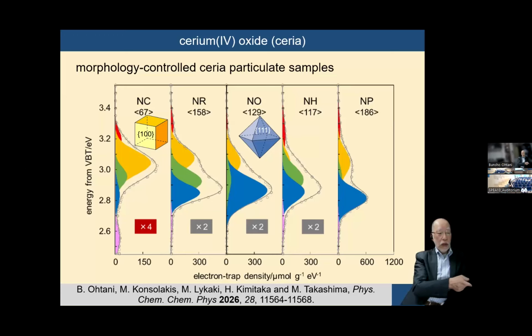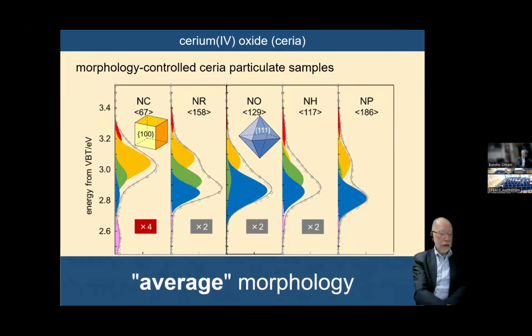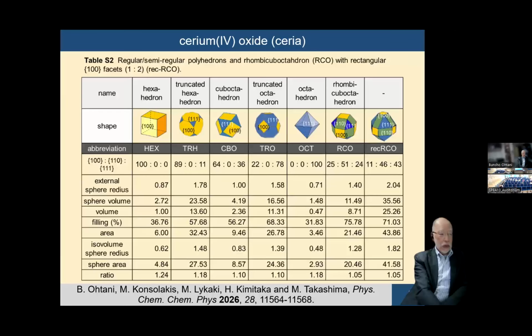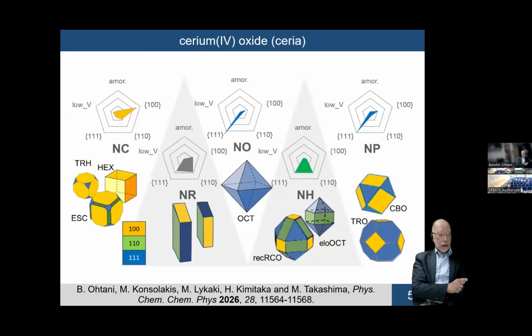And the octahedron particle, the center one, is exposing only the 111 facet. But actually, that is not solely exposing 111. So then we introduced the average morphology, starting from regular and semi-regular polyhedrons, and the 100, 110, and 111 proportion ratio can be obtained from these. So from the ratio of exposed facets, we can introduce the average morphology. And actually, the cubic sample, NC, is not a complete cube. That is an edge-shaped one. And the important point is this radar chart.